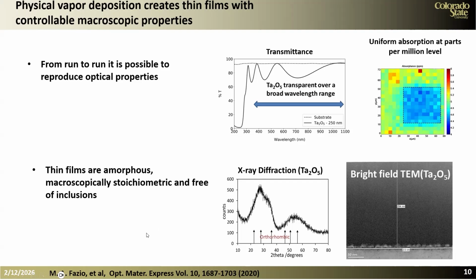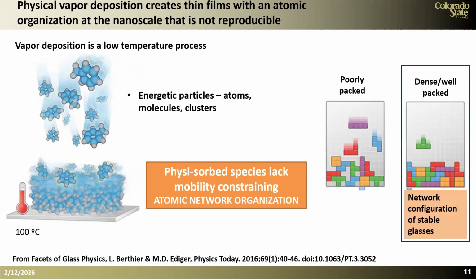If we take it to an X-ray machine, then what we will see is that these materials look amorphous. I show here where the peaks, for example, for tantala of the crystalline material should be, and you see very broad peaks. This tells me that they are amorphous. And the TEM picture shows me that there are no inclusions or nodules when you grow by ion beam sputtering.